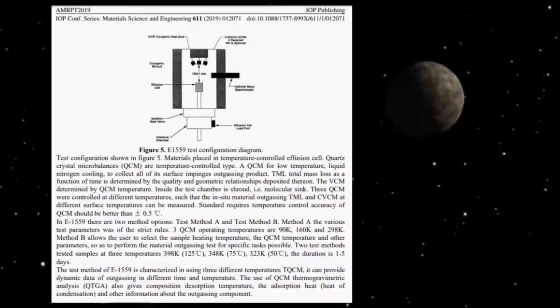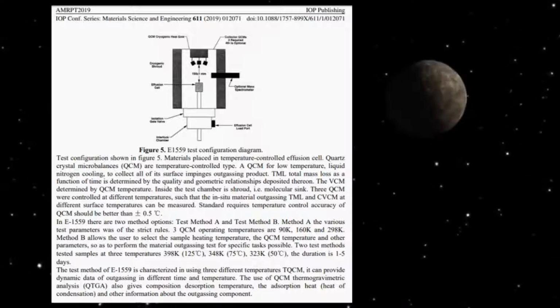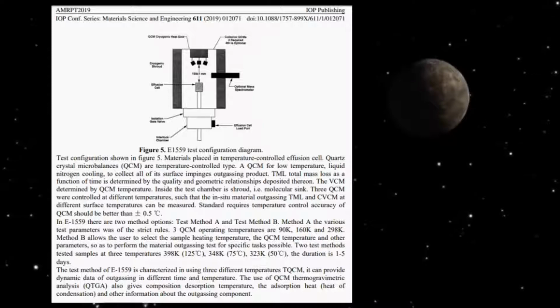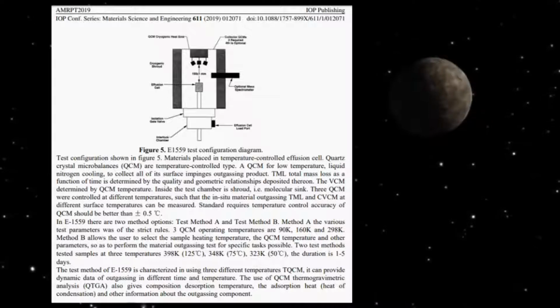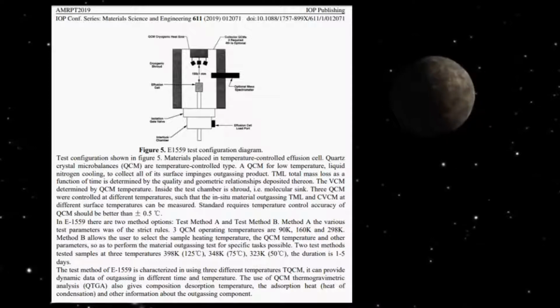The standard requires temperature control accuracy of the QCM to be better than plus or minus 0.5 Celsius. In E1559, there are two method options, test method A and test method B. Method A has strict rules for the various test parameters. The three QCM operating temperatures are 90K, 160K, and 298K. Method B allows the user to select the sample heating temperature, the QCM temperature, and other parameters so as to make material outgassing tests for specific tasks possible. The two test methods test samples at three temperatures, 398K, 348K, and 323K. The duration is 1 to 5 days.